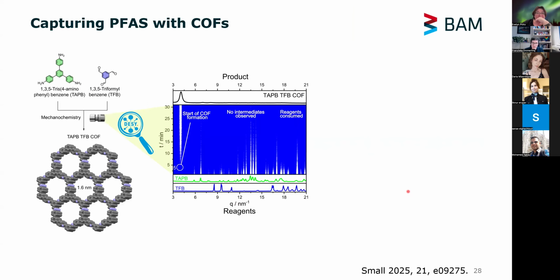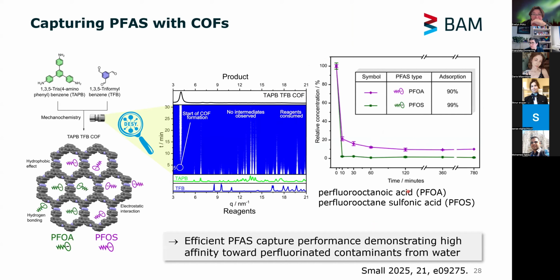And these investigations were done at DESY, and it's also a lucky coincidence that there's a beamline that has a mechanochemical setup equipped for most of the time. You can also perform the reaction there. And then we demonstrated that this COF is quite efficient in terms of completeness and also the time it needs for adsorbing, in this case, one of the two prominent PFAS molecules in water.